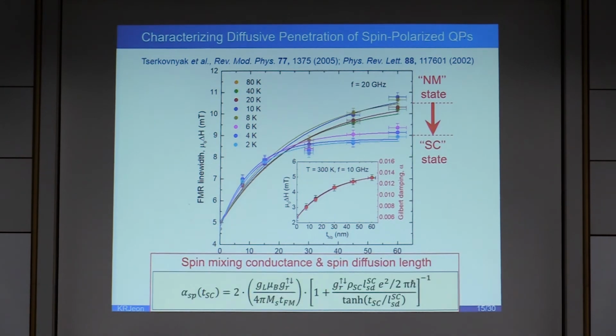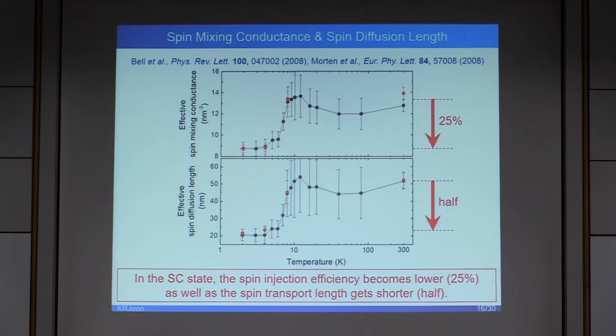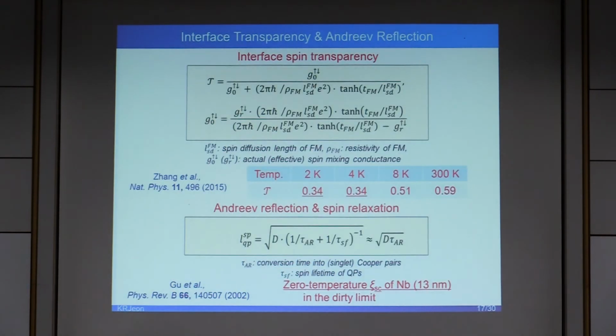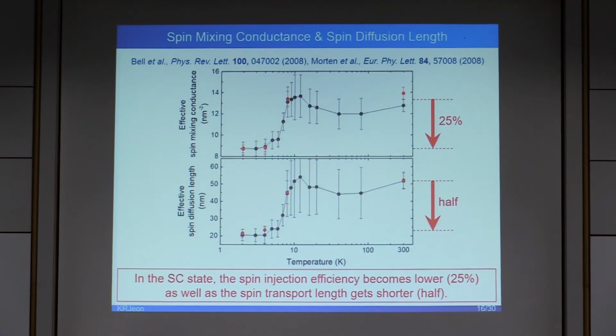For quantification, we have estimated two essential parameters, spin mixing conductance and spin diffusion length, which govern the spin transport properties, by fitting the niobium thickness dependence of FMR line width with this equation. The estimated values are summarized in this figure. This result quantifies that in the superconducting state, the spin injection efficiency is reduced by approximately 25%, and the spin transport length dropped to approximately half of that in the normal state.